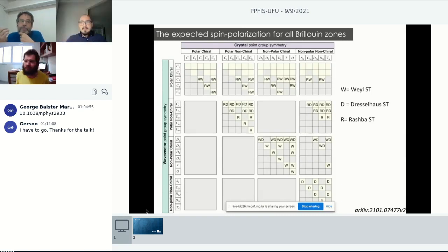So the rule would say that you shouldn't have spin orbit, right? Because you have a centrosymmetric system. If the system is centrosymmetric, then you shouldn't have Rashba, for example. But he found out that there was a huge Rashba effect in each one of the planes. So I think it's more or less what you were describing in your talk, that global symmetry doesn't tell the whole story, let's say.